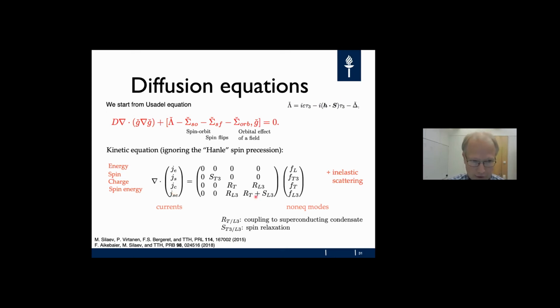The type of relaxation you get in this description is spin relaxation, but also these R terms here describe a coupling to the superconducting condensate, so they eventually relax some quasiparticles into the Cooper pairs.